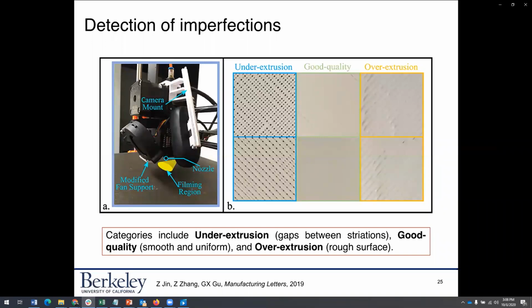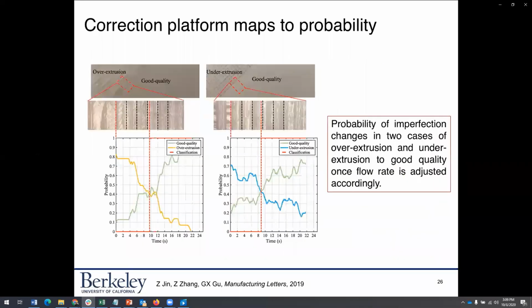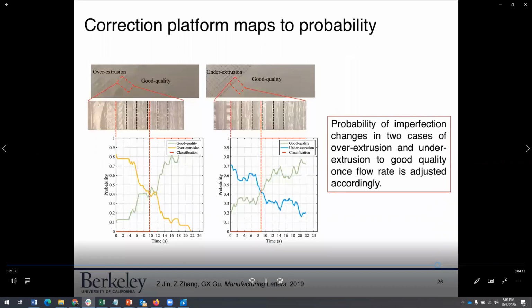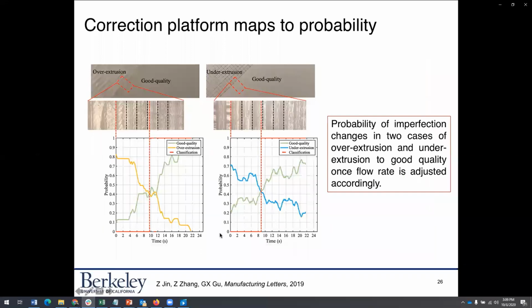Now, these imperfections are in plane. So we have our camera, and we're taking images of the film area in the plane of the sample. Now, this is in general how this platform works. What we're really capturing is the probability of these imperfections happening. In the very beginning, you can see this is one sample. The sample has lots of pores, and so the platform has detected that it is undergoing under extrusion.